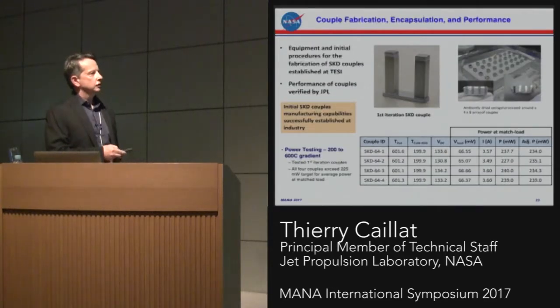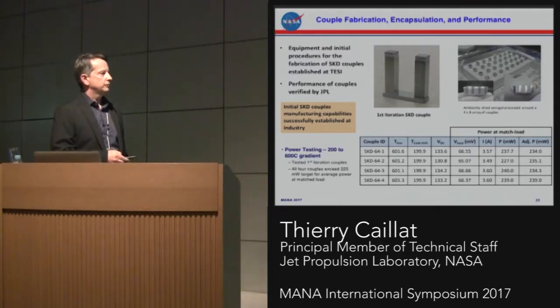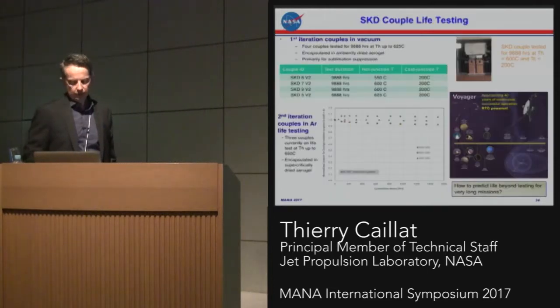The couples themselves have been generating the power we were expecting. We have a lot of tests on those couples. One of the things in the module is using thermal bulk insulation, and we're using a silica-based aerogel for this, which we cast around the couples. This is a sample of a building block of a 48-couple module. The aerogel is not only used as bulk insulation to maximize the thermal efficiency of the generator itself, but also to reduce the sublimation, the vaporization of the materials near the hot side of the skutterudite elements, which will happen, but we just need to control it to an acceptable level.